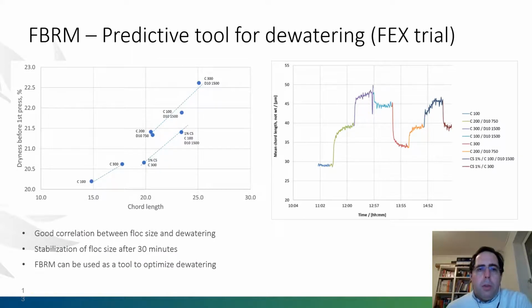Another way that we have used to follow and, as we said, to improve the quality and the dewatering is with the FBRM tool. What we see now on the screen is the evolution and the relationship between the chord length, that is the particle size, and the dryness before press on our pilot paper machine in Stockholm. On the right side, what we see is the evolution over time of this average particle size. And what we could see is that there is quite a clear relationship between the particle size and the dewatering. That will allow us to follow and to optimize the system continuously.